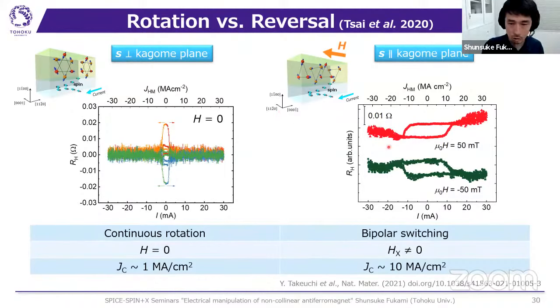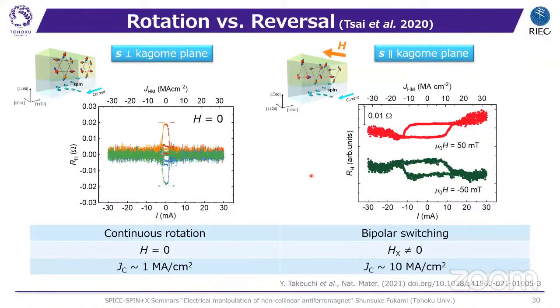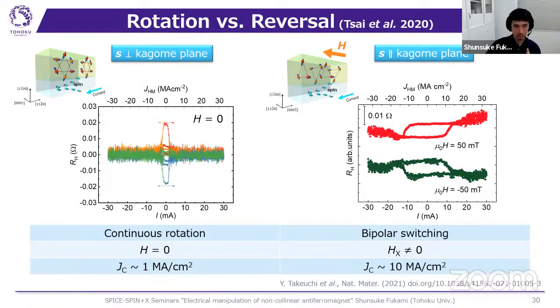So are you talking about this slide? Yes and no. Hysteresis is not in the magnetic field, but I do not know how you apply, how you change current in the experiment. Do you change current smoothly from 0 to higher values, or do you apply some current pulses for each current value which you show on your graph? We applied a pulsed current. So we apply a pulse current and turn off the current and measure the Hall resistance. And then we apply the second pulse with different magnitude and measure the Hall resistance.